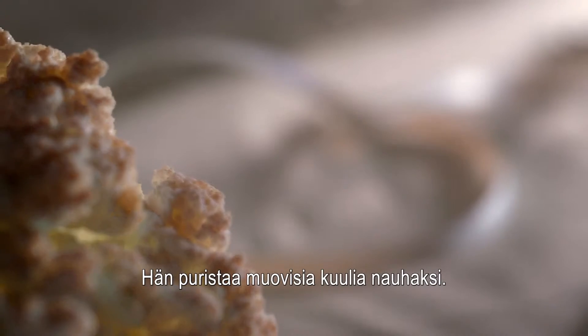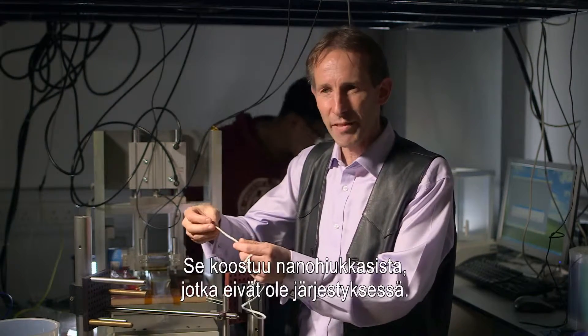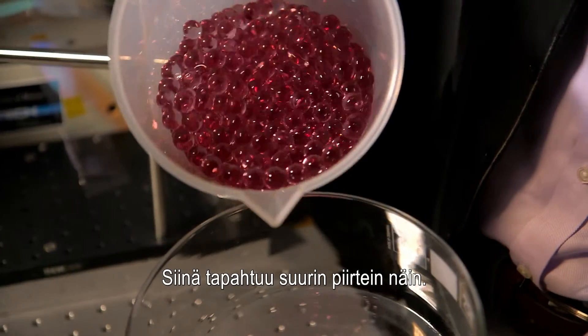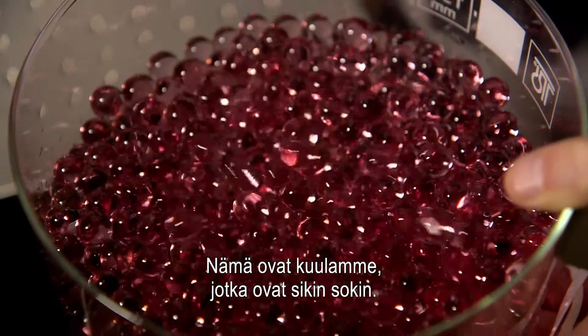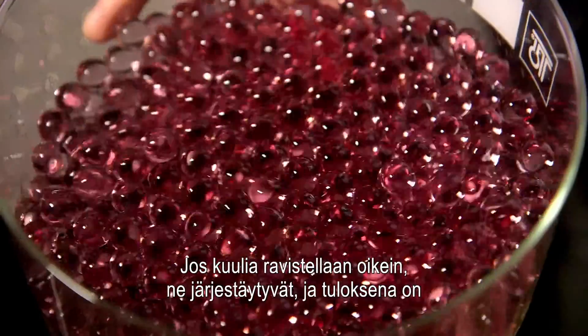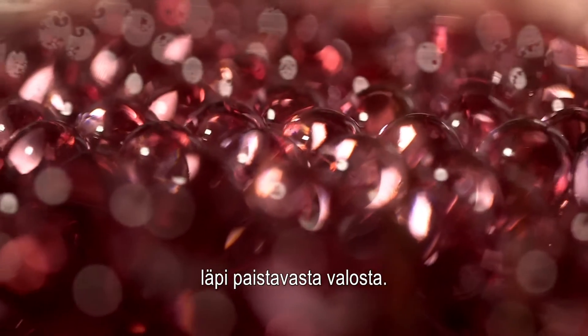To do that, he squeezes a mass of plastic spheres into a tape. This is the tape we've just produced from the extruder, and right now it's just a mass of nanoparticles not in any particular arrangement. So the first thing we have to do is make a film. These are our spheres — that's disordered. But if I just shake them around, what happens is they start to form a really nice lattice, just like the oranges on the stall. If we shake them in the right way, we get perfect ordering, and then we get a beautiful green or red colour from the light scattering through this structure.